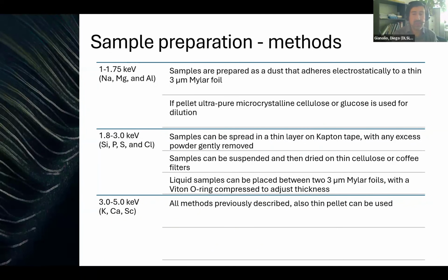Moving higher up in energy, it is possible to deposit a bit more of sample. So a common procedure would be to spread the powder on a thin layer of tape and then remove the powder in excess. Or the sample could be suspended in a solution and then dried on cellulose or coffee filters. And there is also the possibility already to measure some liquid samples, but always using very thin windows and with an O-ring or the possibility to adjust the thickness to a very small amount. Moving to even higher energies, all the methods that I previously described could be used, but it is also possible to start preparing thin pellets and using methods that are more common for hard X-rays.